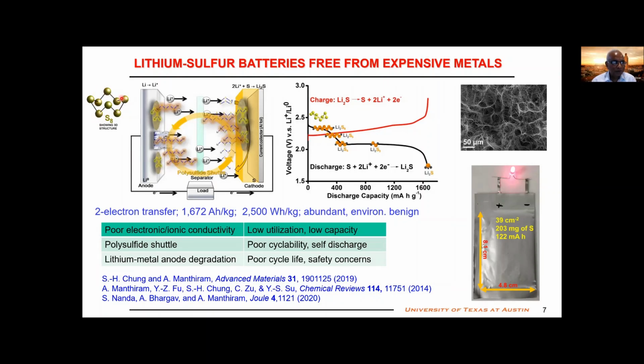In addition to that, sulfur stores 10 times more charge than the other materials I talked about. Sulfur can, for example, theoretically store 1600 amp hour per kilogram, whereas the cobalt-containing materials I showed you earlier, or other materials, store less than 200 amp hour per kilogram. But nothing comes easy. Sulfur has its own problem.